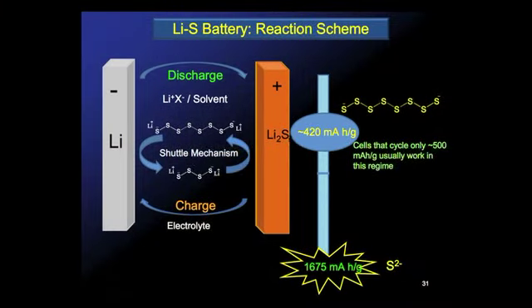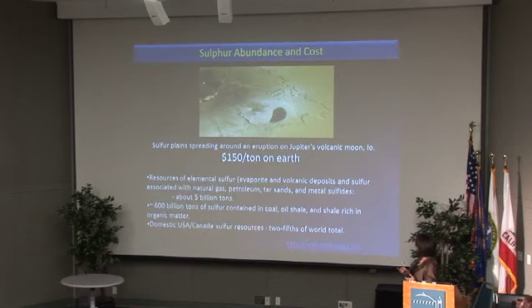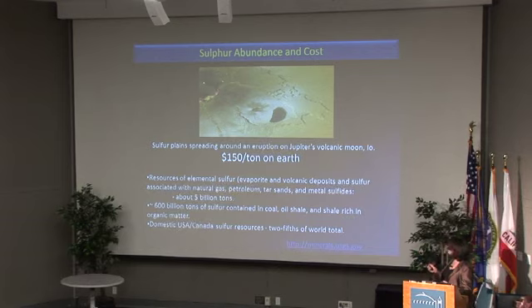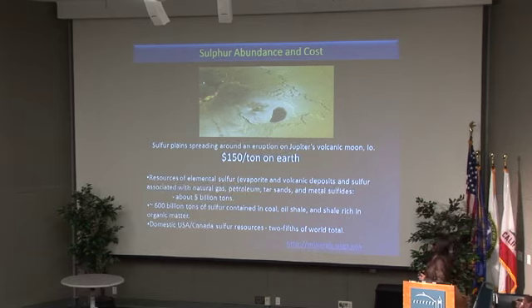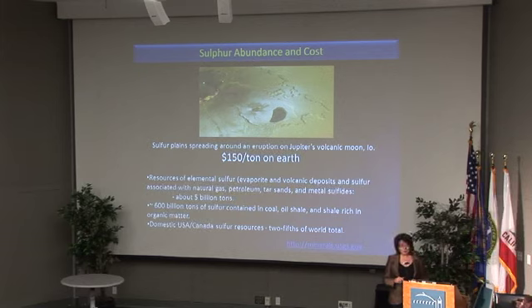So this rather high capacity of 1675 results from the fact that we don't have an intercalation chemistry reaction, we just have a simple reaction of lithium plus sulfur to give Li2S. So I call this a conversion process. The good thing about sulfur is that it's really abundant. If you have to go to Jupiter, there's tons of it there. This is the volcanic moon Io, which is absolutely covered, but there are also $150 per ton on Earth, so we don't have to go to Jupiter anytime soon.